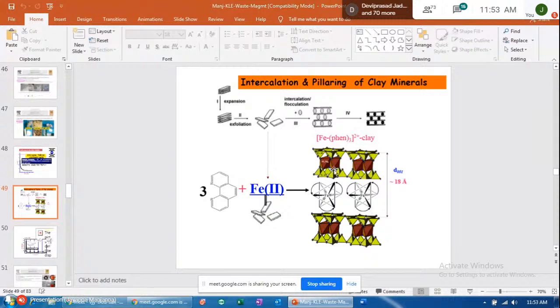Now further, if I heat that material, this chelating agent is an organic compound. For example, in my case, I took a ferrous clay and 1,10-phenanthroline, which is a well-known complexing agent. So you complex it and the layer expands to about 18 angstrom, and then I heat it and decompose it. Thereby all this organic matter goes away, so it forms a pillared clay. Pillared means two layers, and between them there is an iron oxide pillar, like a regular pillar, the oxide itself acting like a pillar.